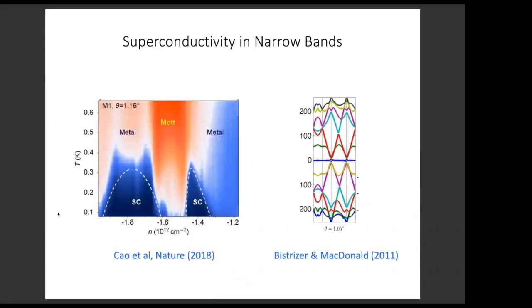as we have seen in the last several years, superconductivity has been found in systems with very narrow bands. Here in magic angle graphene, the bandwidth of the flat band is probably only on the order of 10 millielectron volts, and yet we find superconductivity over a wide range of filling of these flat bands.